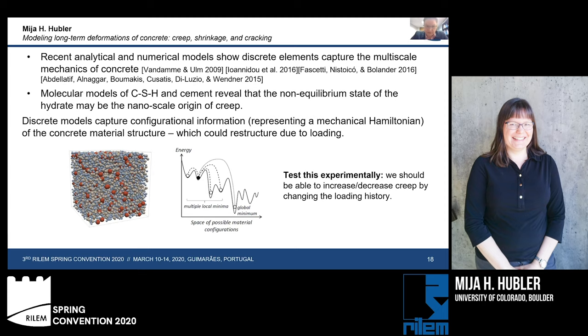And when we load it, it can actually restructure, which something like a continuum or finite element model might not be able to do. So here I have a figure taken from someone else's work that shows an example of such a discrete model. Now this particular configuration of material seems random, but it describes a possible material configuration for cement. In an energy landscape, it might represent this black point here. Now that black point, if it is truly not in the lowest equilibrium state, we could input additional energy to move this state to another local minima or the global minima. This should change the long-term behavior of the material.